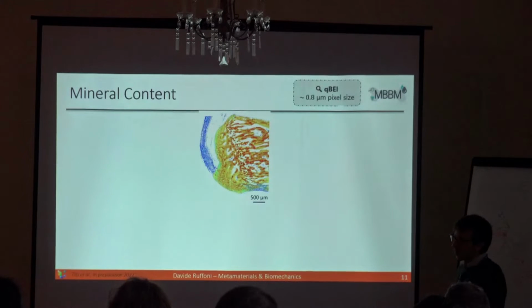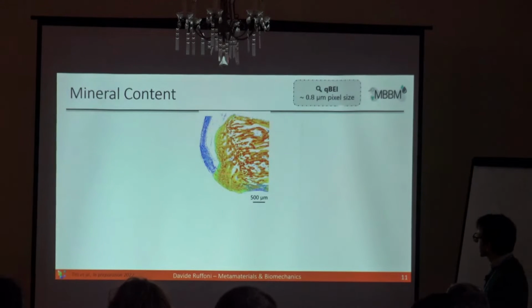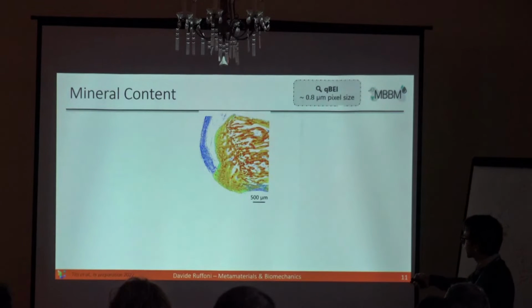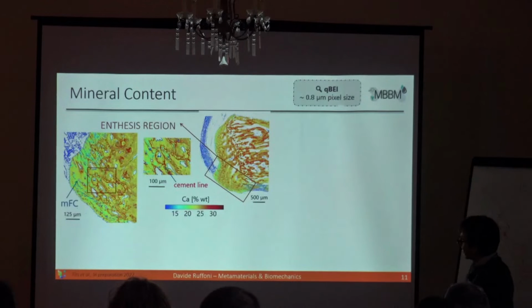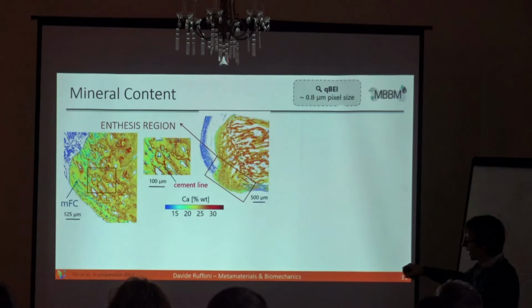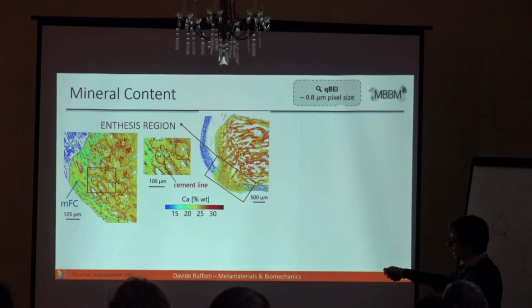Then we look at the mineral content, so how mineral is distributed in bone. These are 2D high resolution quantitative maps of mineral content that we measured with backscattered electrons. So this is the tendon, not mineralized, and this is the bone. What we see is that, first of all, there is a line appearing very red here, which we call the cement line, and this very red line means high mineral content, and this is a kind of glue interface which is gluing fibrocartilage to bone.